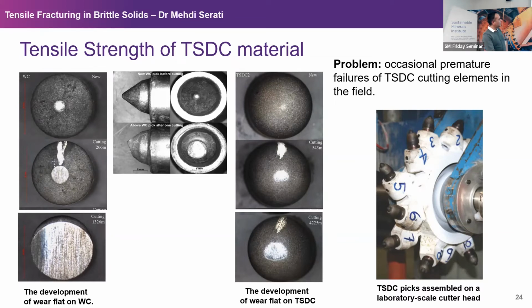But look at the TSDC cutting element. Although this cutting element has been used for 4.2 kilometers of cutting, which is almost 4 times the previous experiment, you see that the tip is barely touched. So it means that it has a superb wear resistance, very promising.